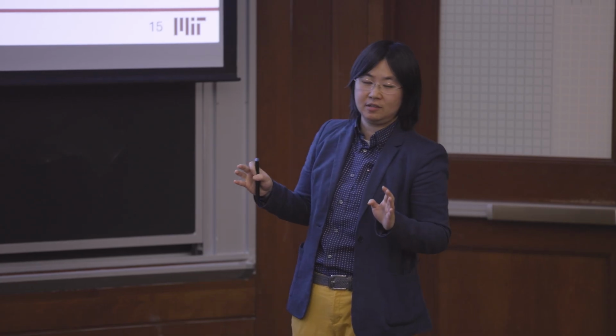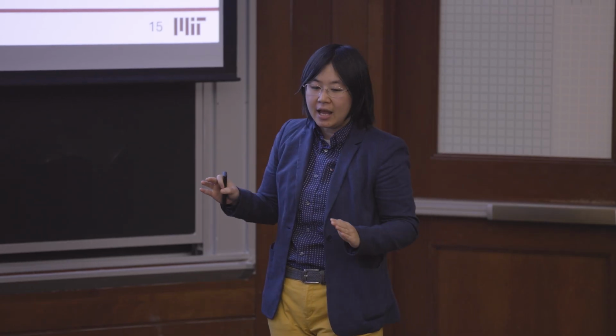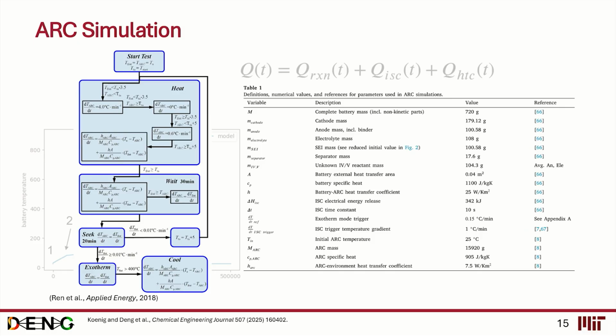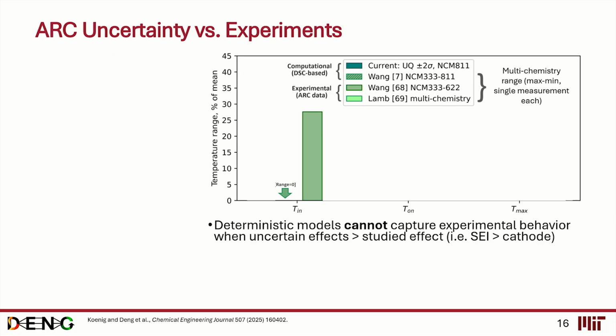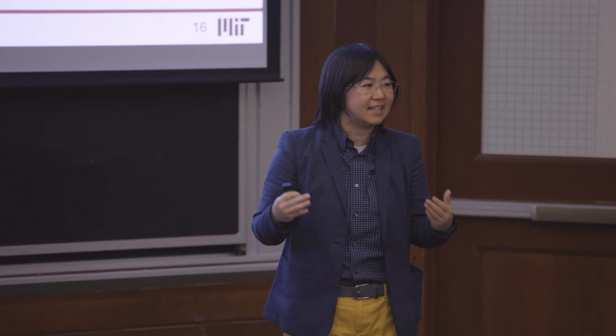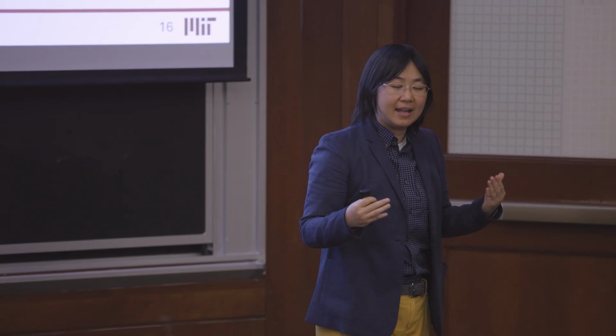All right, so this whole process is done in an experimental setup called ARC, and we can try to capture the dynamic procedures via this quite complicated diagram. And then we can get as many as possible of the parameters that describe the mass and internal short circuit, etc. And we utilize the model that I just described to you, that Ben developed from the CRNN approach, to model the thermal runaway. Here is a very busy plot, but I'll try my best to explain how we take our full model and try to understand the dynamics that we observe in the cell level experiments.